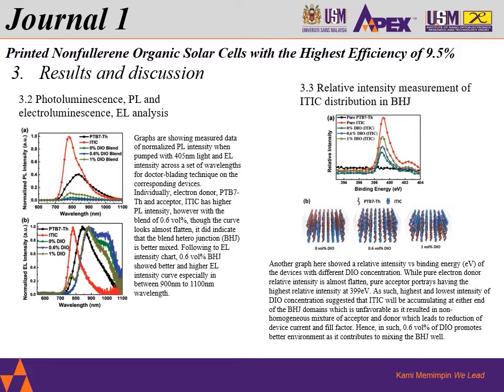Then next, relative intensity measurement, ITIC distribution in BHJ was also measured and reported. So on the top here is the graph of the intensity of ITIC, and then the binding energy. We have this peak as the binding energy, and pure ITIC, of course, will have the highest relative intensity.